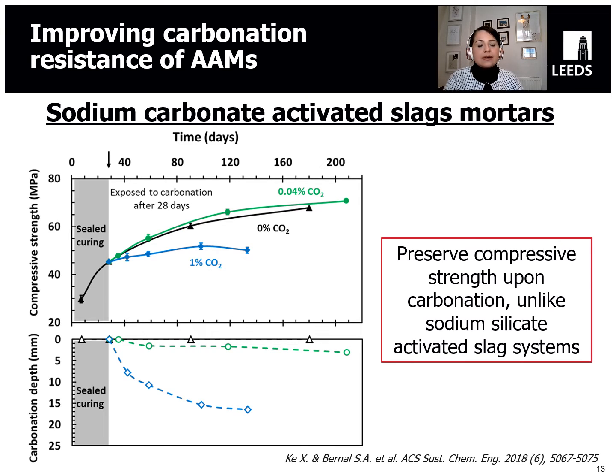So we can see here that the material is still carbonating. This is the blue line. However, the compressive strength is not changing, which I will say is the ideal outcome. We want our materials to absorb as much CO2 as possible, but we don't want that carbonation process to compromise the performance of the materials that we're producing.